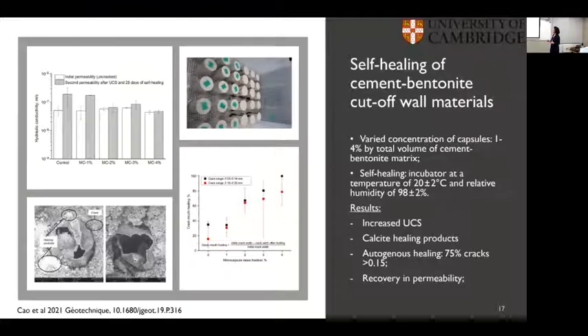Another thing that I would like to cover, when we are talking about the gelatin gum arabic microcapsules, was a work developed by Beni. Beni is going to present some of his work in the talk with Shipriya in a bit. He also investigated the use of the same microcapsules for self-healing of cement bentonite cut-off wall materials. What he noticed was an increase in the compressive strength of the cement bentonite systems and an autogenous healing of these cracks: 75% of the cracks, when we are talking about cracks larger than 0.15 millimeters, and a recovery in permeability as well.